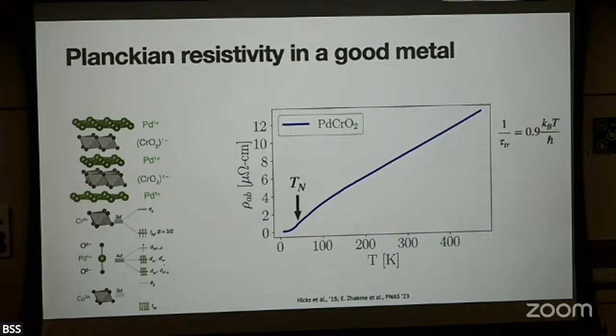So does the chromium oxide also exist in isolated form? So when you say that chromium oxide is a Mott insulator, what do you mean? Oh, from magnetic measurements, it exhibits Curie-like susceptibility. And in neutron scattering, we've measured the spin correlations. And no charge fluctuations? No. Yeah, so the Mott insulator is not doped by the palladium electrons.